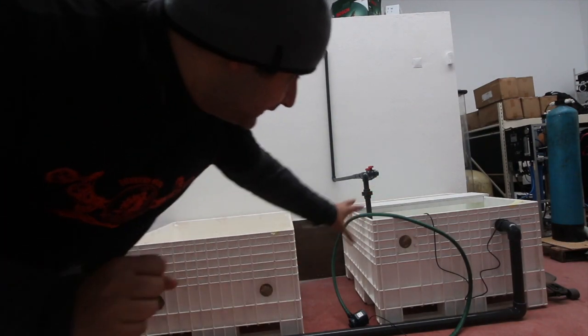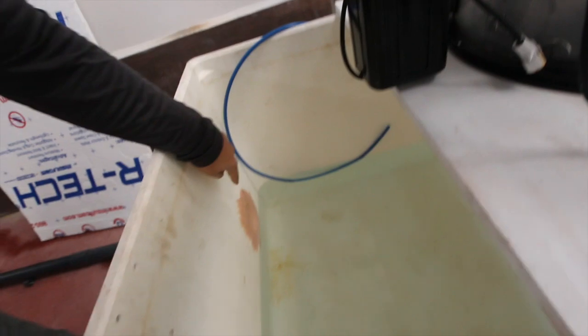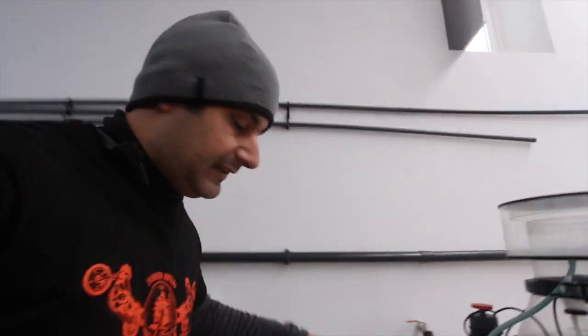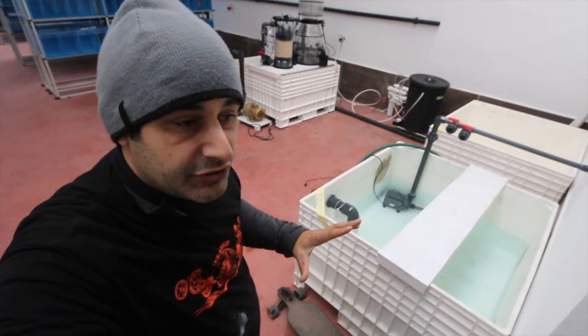Now, it seals the water. I tested, it sealed the water very well, no leaks, except on one, this one, but that was the first one that I did. I didn't clean it properly. I just used the rag and cleaned it. I didn't sand it, and I didn't use acetone or any chemical cleaner like that. On the other ones where I used PVC cleaner, it actually held very well. Now I tested, no leaks, which is good.